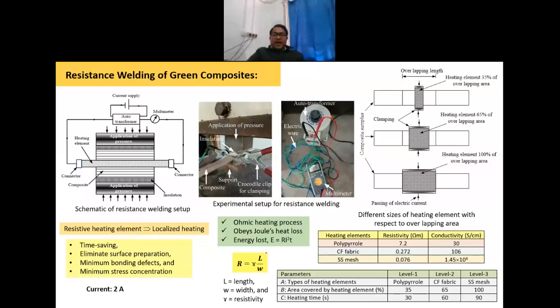So what happens basically, at the joint interface, you keep a heating element. It has to be electrically conductive. So if you apply voltage to this heating element, it will heat up, because it has some resistivity. Any conductive material you can consider, and it will have some resistivity.